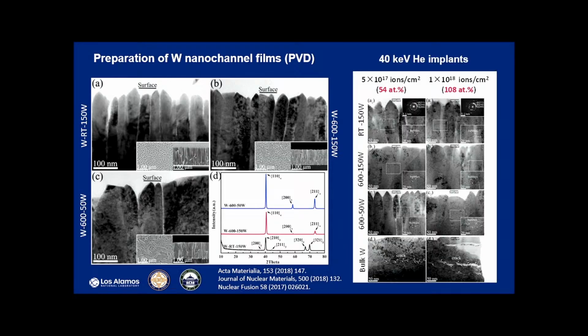And for one of the textures, once you have those, you do a very high fluence of helium implantation to look at where the helium ends up, to see if you're going to see a crack there. So in the bulk tungsten, we see cracks already in that region. But for the other three films, we did not. We see many bubbles, but no cracks yet.